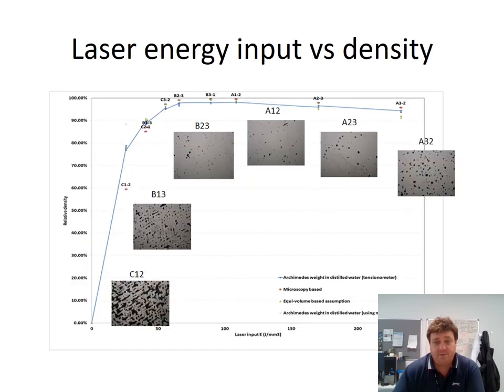And we'll measure, for example, density. And that will show you here what the result might be from an experiment like that, where with a low energy density, we're looking at very low densities and high porosities. So this C12, you can see that the laser hasn't quite covered the entire cross-section of the cube, and it leaves quite large pores. The porosity goes down and the density goes up as we increase the laser energy density till we get to an optimal point up at the top of the curve, around about here. And that would correspond to A12 might be our best option here, with the lowest porosity, in the region of about 1 or 2%.